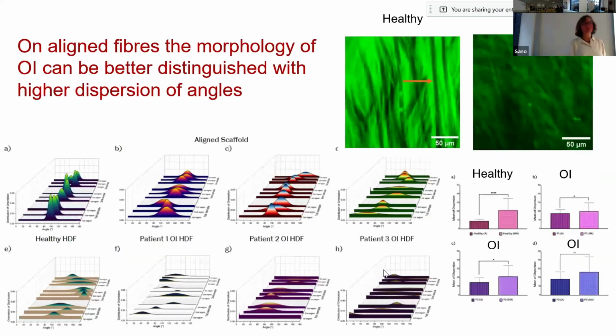So the idea is that when we use these aligned fibers, we can straight away see the difference between a healthy and an osteogenesis imperfecta cell. Here we've collected only fibroblasts from the skin, because it's difficult to collect bone from somebody with a bone disease, as you might imagine. But the fibroblast alignment does happen on these scaffolds as well. We can see healthy cells aligning nicely, or patient cells, although they do align, much less, more of a spread. And if we don't have aligned scaffolds, we don't get this alignment.